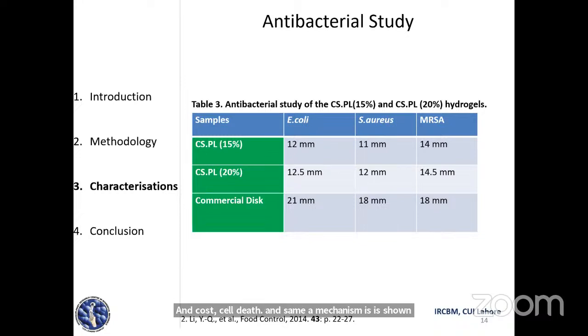They electrostatically bind with the surface of the bacterial membrane. The positive charge of the PL interacted with the negative charge of the lipopolysaccharides and proteins of the bacterial cell membrane. When the electrostatic interactions increased in number, the bacterial membrane structure got disturbed by the change in permeability of the bacterial membrane. These interactions interfere with essential nutrients getting inside the membrane to the cytoplasm. As a result, the bacterial membrane got fractured and the bacterial cell was damaged by PL.